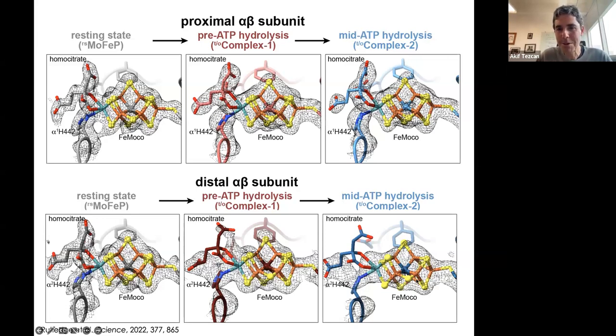So these blobby structures are probably superpositions of many different intermediate states found in solution, and they do not fit with the resting state coordination of homocitrate and histidine. That implicates molybdenum in the activation of nitrogen. Unfortunately, we don't see any nitrogen bound. We don't see any substrates or intermediates bound, and we certainly cannot see hydrogens at this resolution. But at least these structures tell us that we can start to capture this very enigmatic protein and its cluster during turnover. What we're hoping to do now is tweak the turnover conditions so we can get substrates and inhibitors populated in large enough abundances to see them with Cryo-EM.